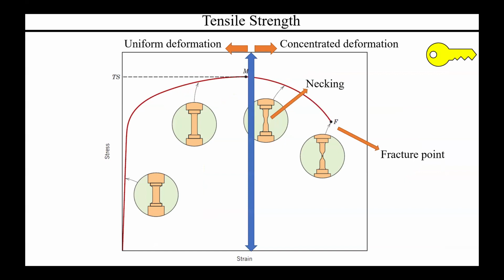So the tensile strength represents our transition between uniform deformation and concentrated or localized deformation. Prior to the tensile strength, you're getting uniform, homogeneous stress applied throughout the material, which is making it stronger. We'll talk later in strengthening about what the actual mechanisms behind that are. But once you reach that M point and transition beyond it, you're getting localized stresses. The stresses build up in certain spots, giving this necking behavior, at least in a ductile material, until eventually you hit that fracture point.